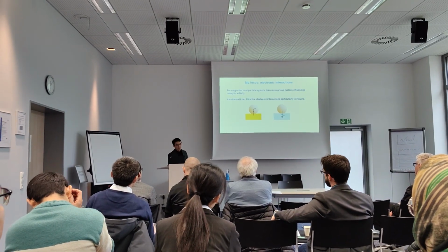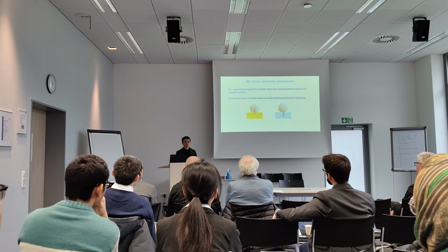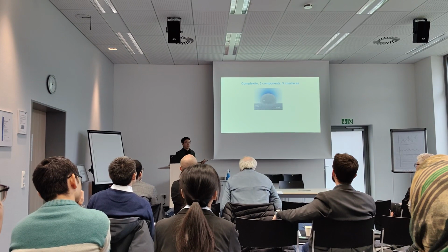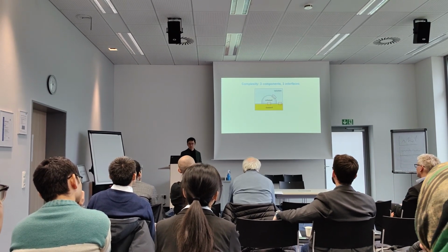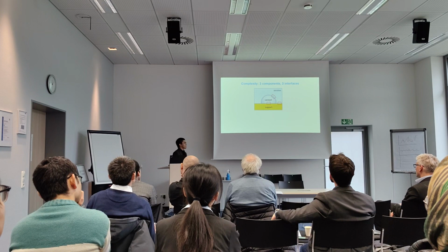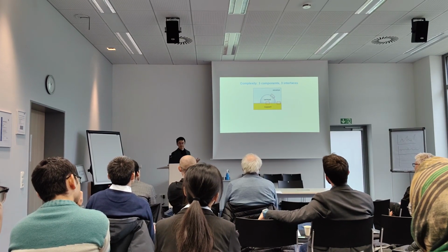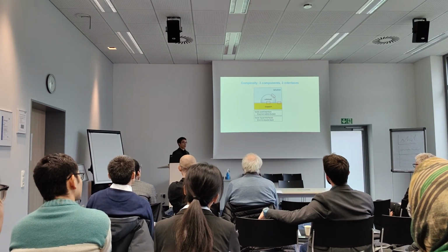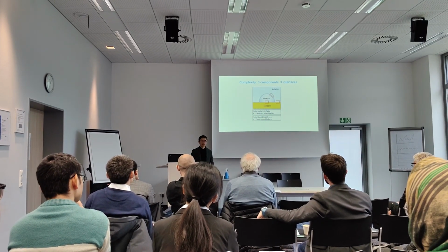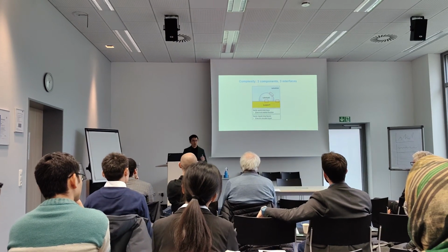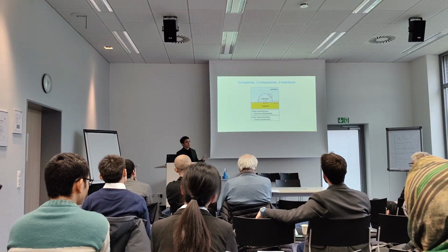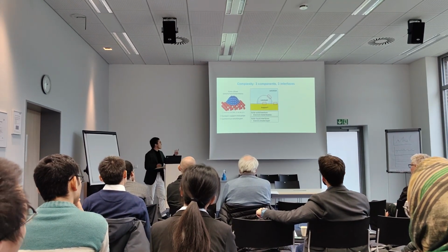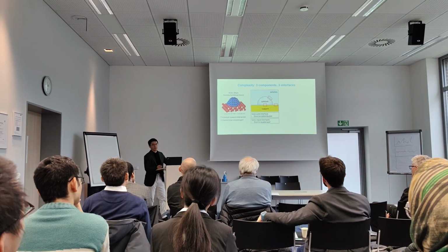As a theoretician, I find the electronic interaction particularly intriguing. This system is very complicated in that it has three components: the nanoparticle, the support, and the solution, and the three interfaces formed in between. At the solid-solid interface, electron redistribution occurs. At the solid-liquid interface, there are electrical double layers, where we need to resolve the potential distribution and the ion and solvent distributions. The state-of-the-art quantum mechanical description for this electronic system is Kohn-Sham density functional theory.